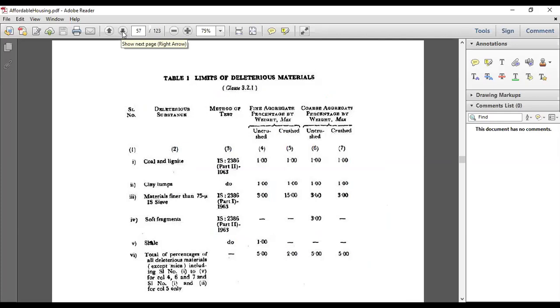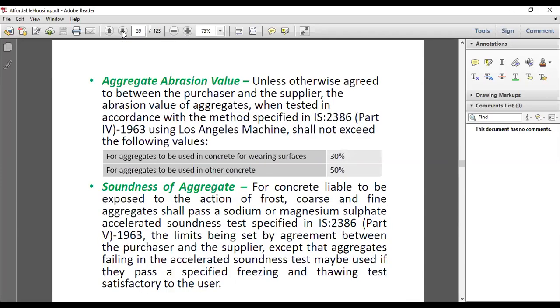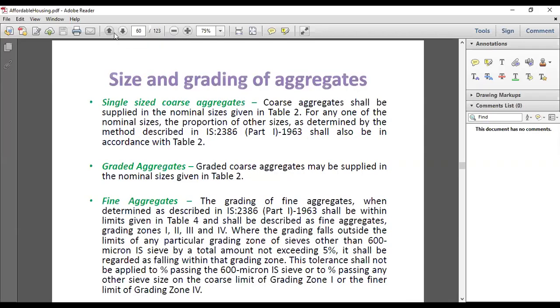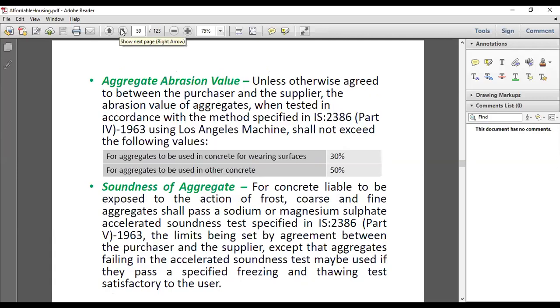So this has to be removed because aggregate gives the strength. Cement's role is only binding. Cement doesn't give any strength. The strength is given by the aggregates. So they have to be perfectly graded, so that there is full packing and there is no void available for the moisture to ingress. So these are the tests that we do. Aggregate abrasion test: if you are going for road construction, then you have to do the abrasion test. Similarly, you have to do the soundness test.